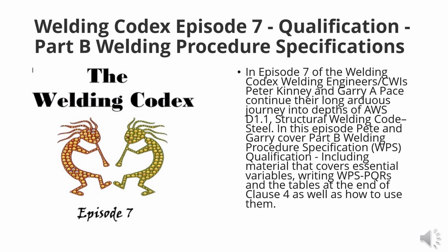You're right. Always look for the word omission. And then we've got preheat, decrease of interpass temperature, and then the addition or deletion of post-weld heat treat. Most of the time you're not going to get tripped up on post-weld heat treat, but generally any weld procedure I write, I throw in there none. Exactly. The preheat temperature, you've got to have that in there. And if there's a decrease in preheat temperature by more than 25 degrees, so if you qualify it at 200 degree preheat and you want to have the weld procedure run at 100 degrees, nope, you've got to requalify it. And the same with the interpass temperature.